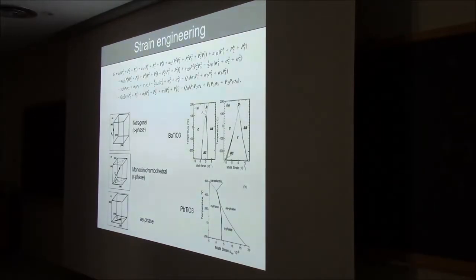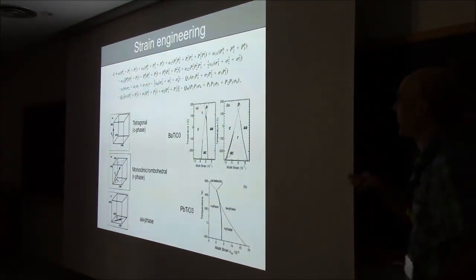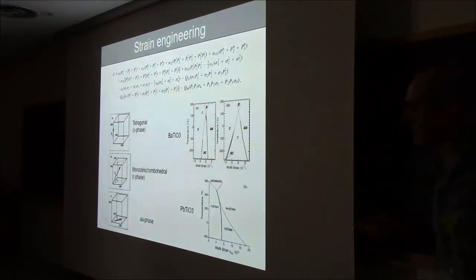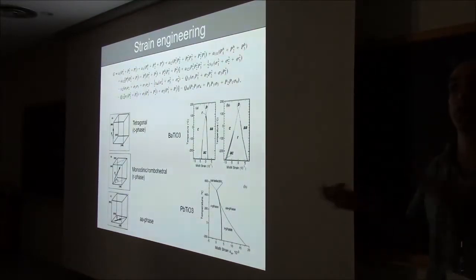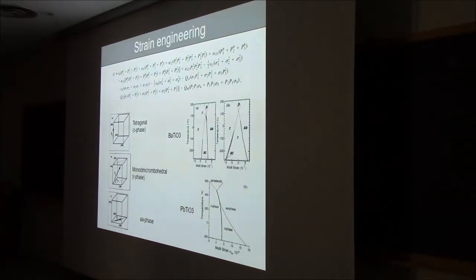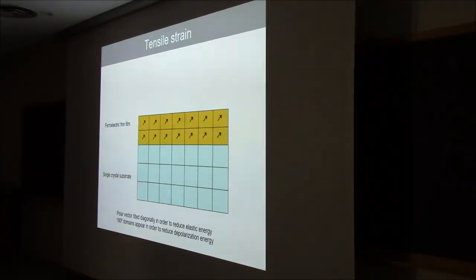And then you can get as sophisticated as you want, or as you can, which I can't, but people cleverer than me can. So you can use Landau theory to calculate what kind of strain you should impose onto your ferroelectric to induce different polar symmetries that are not just your classic tetragonal up and down, but tilted polarized states. These are the kind of games that people play with ferroelectrics, and it's called strain engineering. And since this is an introduction, you should know about it.